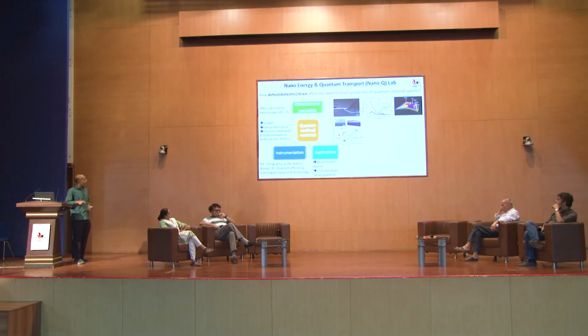Okay, in another work, here by applying strain at nanoscale, there the application of strain is a little bit tricky. There are pillars which are spaced 52 nanometers center to center. Okay, you place a monolayer on top of them and you see how their property changes. And what we found is that the dark exciton now gets brightened because of this application of strain at the nanoscale.